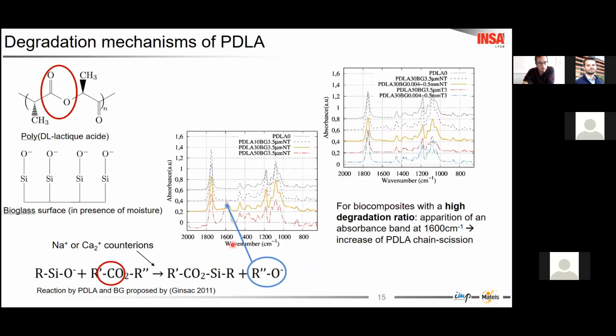So we took the samples that had the most signs of degradation, and by infrared spectroscopy, we observed the chemical bonds in the sample. A peak absorbance band at 1600 can explain the chemical reaction that degraded our PLA.